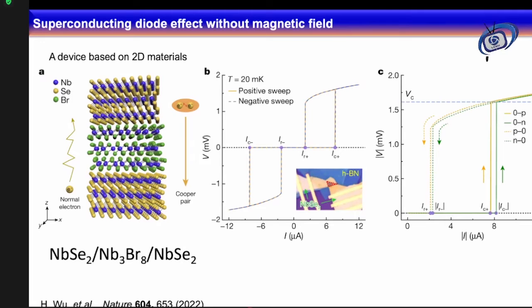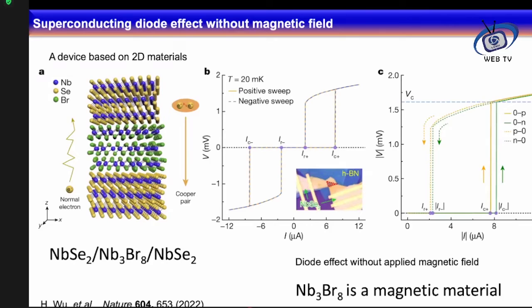And the interesting point of this discovery was that in this case, they do not need any applied magnetic field, and they can actually do it without a magnetic field because the inversion symmetry is broken at the interface, and this central barrier can have some magnetic effect, and that magnetic effect will break the time reversal symmetry. So now you might have both broken symmetries in this device. So then you can actually have this diode effect in a Josephson junction.